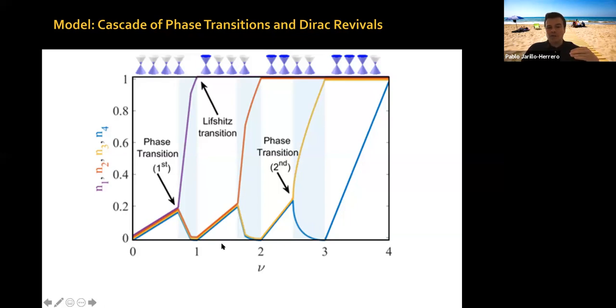When you are near nu equals two, which means you have put almost one third of an electron in each of the three remaining flavors, the system decides to do the same thing again. Rather than filling the remaining three flavors uniformly, it again breaks the symmetry between these remaining three flavors, fills one completely and empties the other two, so that we go back to charge neutrality, and so on and so forth. Now these two flavors get filled. And depending on parameters, this can happen as a first order or a second order phase transition. There are many details that you can look at in the papers on the theory, but the system decides to fill the remaining last two flavors.